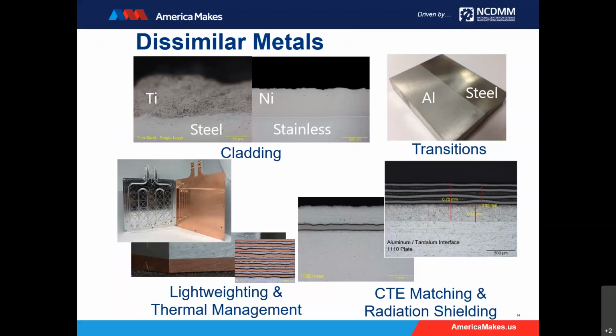The picture on the left is a heat exchanger, which is a great example. Our number one combination is aluminum and copper. Again, copper is heavy, but it wicks heat away great. So mixing those is a good opportunity. The top right is a transition joint from aluminum to steel. Often those type of joints are made with explosion welding. By printing that, you can get a shape that's nearer to what you're trying to achieve and quite often reduce your price. And on top left is what I would consider more of a cladding. So not our traditional 3D printing, but using the welding technique to add an expensive metal A onto a cheap metal B.